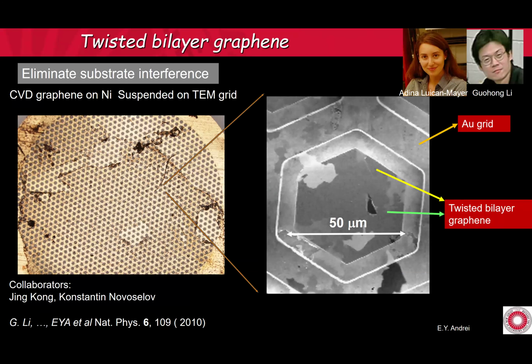Okay. So the next thing is, we wanted to do STM. We wanted to figure out what that gap is from. So we couldn't do it on the suspended samples because they were very small. You can't bring the STM there because it kind of collapses. So we had another idea. Let's have CVD grown graphene and put it on the TEM grid.